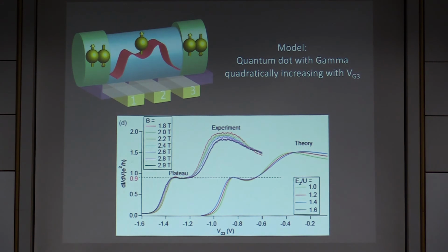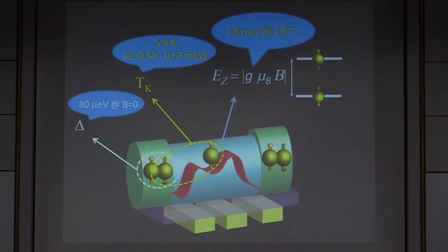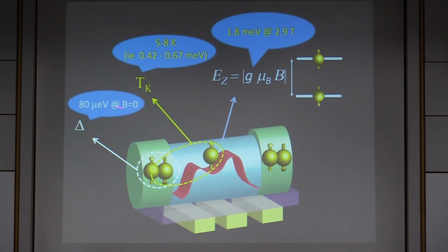And so we decided to investigate this again by modeling with some energy. And also we assume that there is a localized state, and there is a quadratically increasing gamma with the gate voltage, because what we need is a plateau, and then we need to evolve to some kind of non-interacting regime with a constant, or almost constant, conductance. And that can be achieved if you assume that your gamma, your coupling to the superconductor, increases with the gate voltage. So with these ingredients, the problem has the following energy scales.